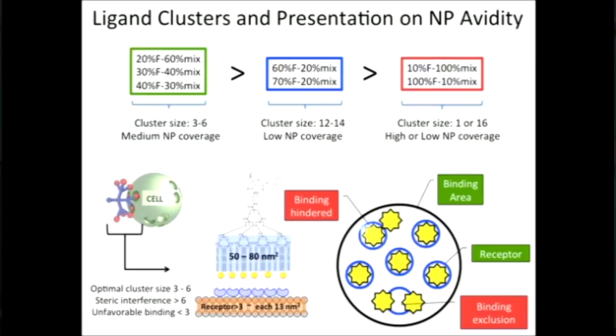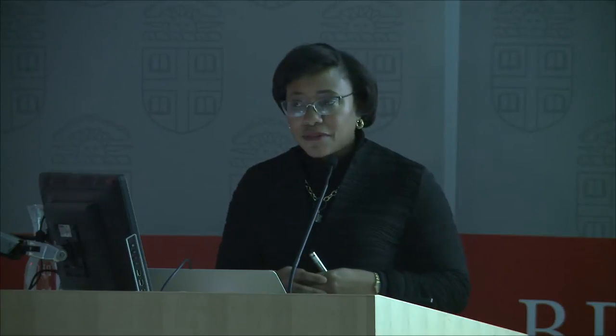Now, if we go to higher numbers, and you remember that we get to a point where we're really losing this game, we think that we're seeing steric hindrance. These folate molecules are getting in each other's way in trying to bind to the folate receptor. We did do the math and the modeling to determine if there is a positive cooperativity between these systems compared to a normal system. And we find that it is actually a negative cooperativity, meaning the more you add, the harder time they have in binding together.